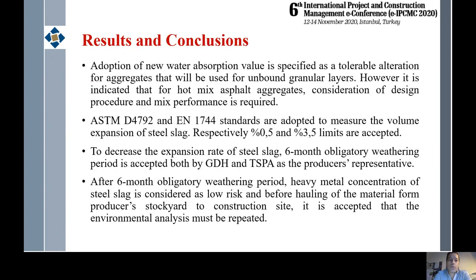And according to these proposed solutions, we have some results, and at the end I will give you the conclusions about our project. Adoption of a new water absorption value is specified as a tolerable alteration for aggregates that will be used for unbound granular layers, which are used in highway construction as base and sub-base materials. However, it is indicated that for hot mix asphalt aggregates, especially for wearing courses and binder courses and stone mastic asphalt, consideration of design procedure and mix performance is required.